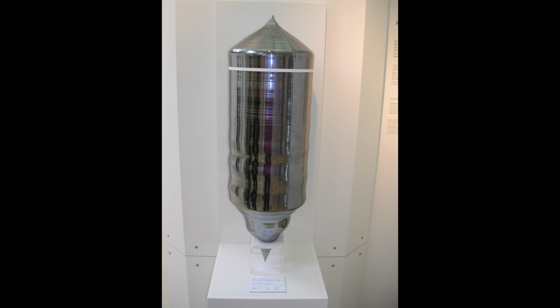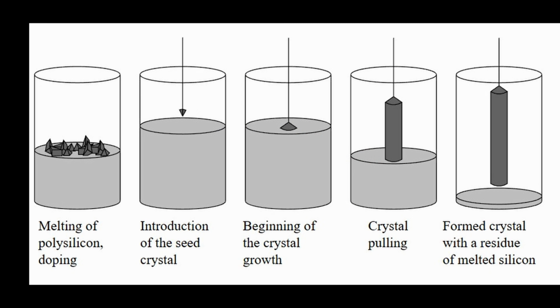You take a quartz crucible, put chunks of high purity silicon in it, and heat it under an inert atmosphere, often argon, until it all melts. Remember, that's above 1400 degrees Celsius. Then you dip a small seed crystal of silicon in this molten silicon. The seed is a perfect crystal oriented in a specific direction. You slowly pull it upwards while rotating it, and as you pull, silicon from the melt solidifies onto the seed. And if conditions are right, it continues the seed's crystal structure.